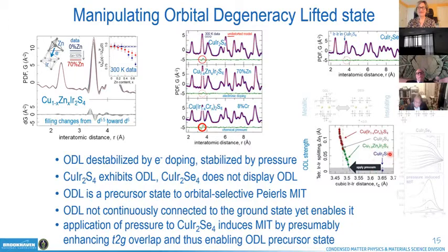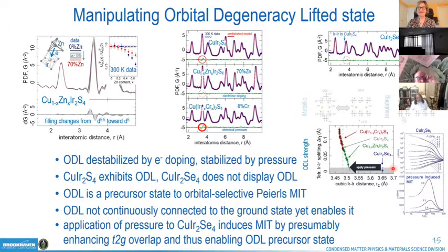And then our sister compound copper iridium two selenium four actually is placed on this diagram right here, which gives us an idea that maybe, just maybe, if you apply pressure and you bring basically the interatomic spacing between the iridiums back to this line, you will invoke metal insulator transition. Interestingly enough, this hypothesis has actually been tested 30 years ago, and people just did not know what it means in this context. And that is that pressure indeed induces metal insulator transition in the selenium variant. So presumably the application of pressure to this system basically induces MIT by enhancing t2g orbital overlap and thus enabling the ODL precursor state. In other words, you can label the selenium sister compound as a latent ODL system, and it only really zings once you apply pressure and you allow for sufficient orbital overlap.